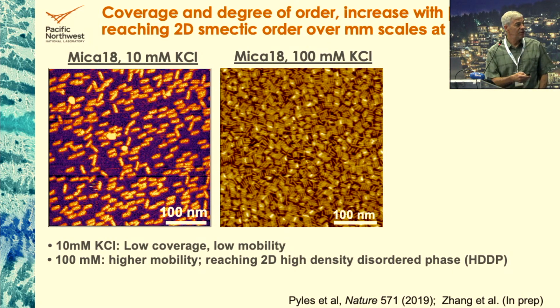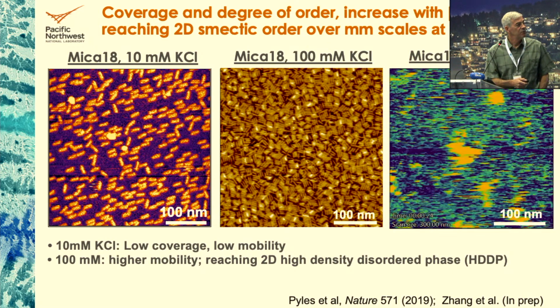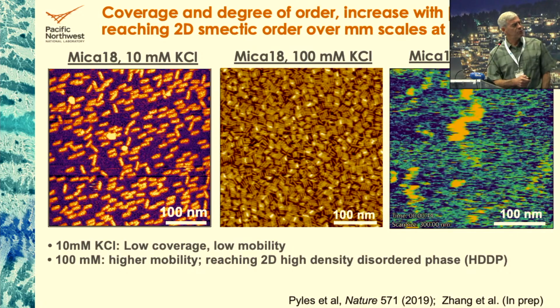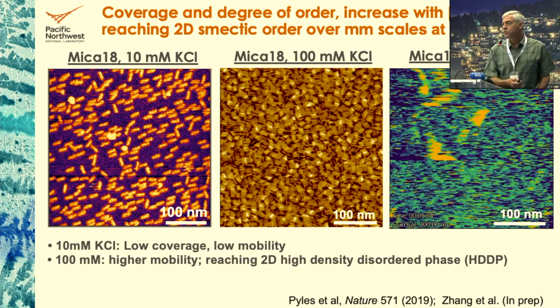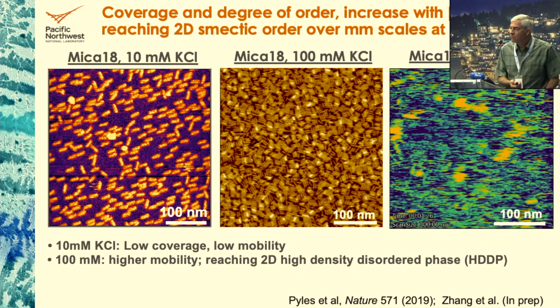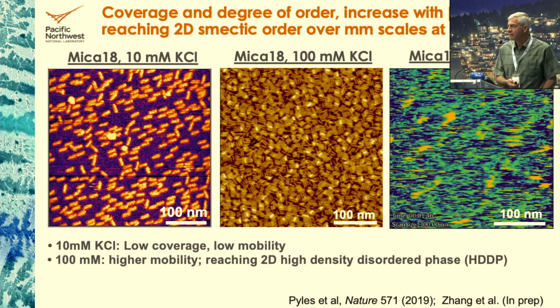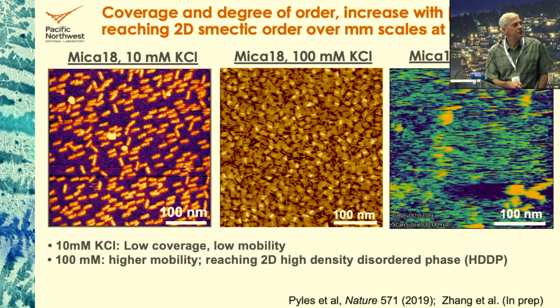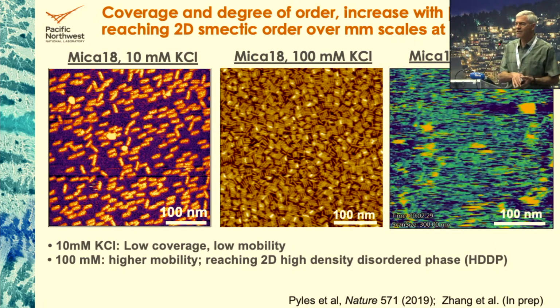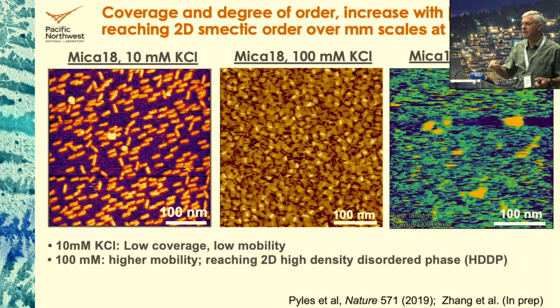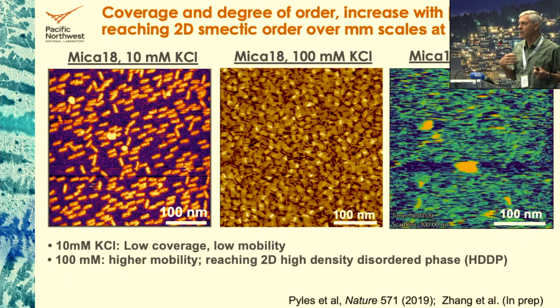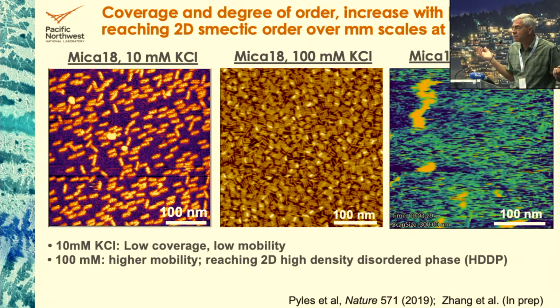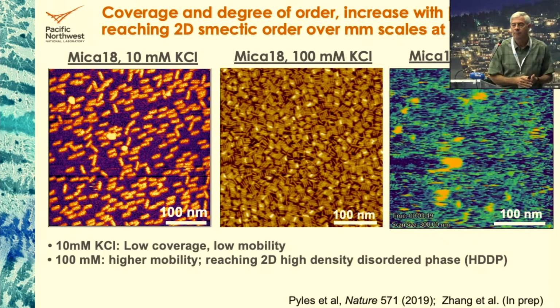If we go to even higher salt concentration, we see something quite different, and you'd say, well, what are we looking at? It's a 2-dimensional liquid. So they're so mobile now that they're essentially a nanorod liquid in 2D. The bright yellow is actually protein stuck on top of the liquid. We don't know if these are mutant proteins, and so there are a few of them that stick. We don't know why, but there's a few of them.